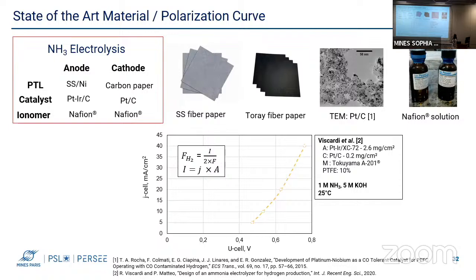This graph represents the only state-of-the-art polarization curves for ammonia electrolysis in AEM conditions. It has been obtained when using at the anode platinum iridium on carbon at a loading of 2.6 milligram per centimeter square, at the cathode platinum on carbon at a loading of 0.2 milligram per centimeter square, and an ion exchange membrane and PTFE as a binder.